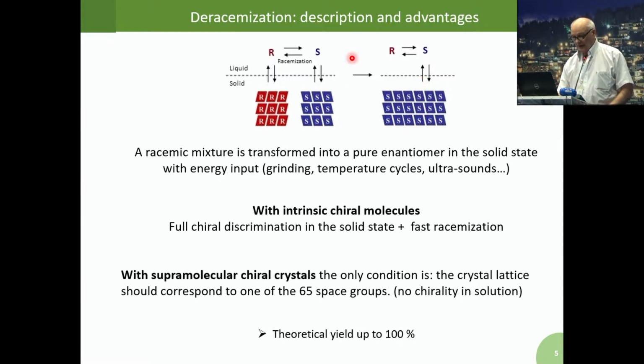So how does that work? With intrinsic chiral molecule, we will suppose that we have what we call in our jargon conglomerate, which means that every enantiomer crystallizes in its own. But we will, in addition to that, suppose that we have also a fast racemization in the liquid state, which means that the two enantiomers can interconvert chemically. Okay, so that could be done by thermal activation, but it could be done also by catalyst, sometimes by protein. And if you have these two conditions fulfilled at the same time, then by applying an energy input in your system, which is very simple, it could be simply continuous grinding, okay, or it could be just temperature cycling.